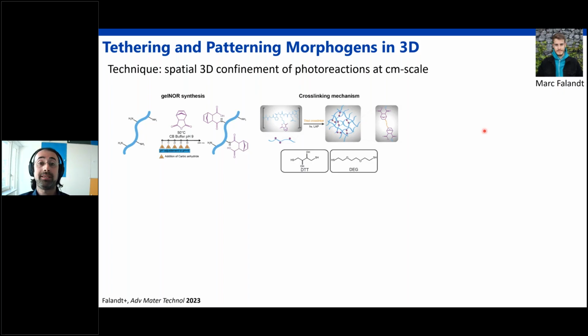And volumetric printing allows us to control these phenomena across centimeter-large distances. So that is something other light-based techniques cannot really do very easily. In this case, we use gelatin norbornene-based biomaterials, which can of course be photocrosslinked by activation through a photoinitiator, again LAP in this case, and in the presence of thiolated compounds generate a hydrogel.